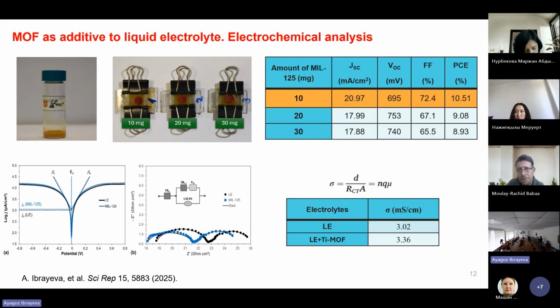When we add only 10 milligrams, it still had the properties of just the liquid electrolyte. We add more to give the MOF a chance to work as a scaffold, as a framework, and prevent leakage by increasing the amount of this powder.